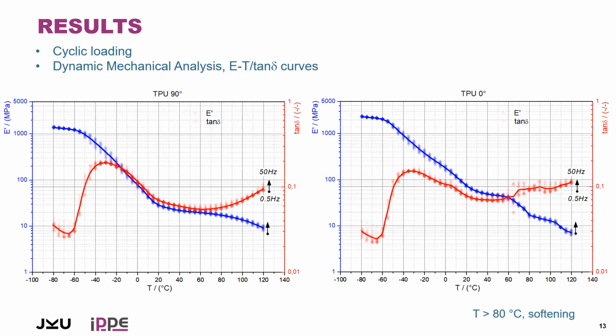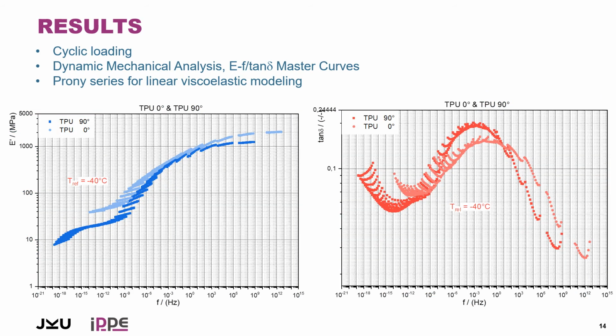And then we can see the classical trends typical for thermoplastic polyurethanes. Interestingly, above 80 degrees C, you can observe a softening. Does it mean the difference between the orientations is vanishing at high temperatures? Furthermore, we also performed this test frequency dependent, in a frequency range from 0.01 to approximately 50 Hertz at different temperatures in order to construct master curves.